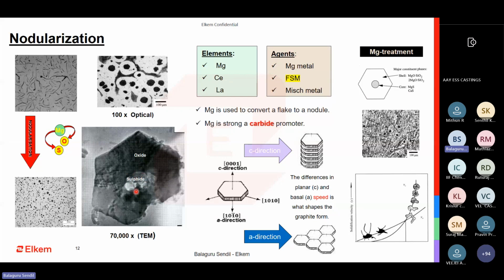To make this nucleus, magnesium sulfide or magnesium oxide, and with recent developments in nucleation theory, we see magnesium nitride is also very important. All these are the nuclei, non-metallic, but all magnesium, cerium or lanthanum based. The process of introducing magnesium to a metal to convert a flake to a nodule is called nodularization. The magnesium you add combines with the sulfur, oxygen, and nitrogen available in the metal, and forms magnesium oxide, magnesium sulfide, magnesium nitride, multiple non-metallic components, and becomes a nucleus, a point where the carbon can deposit, grow, and form a nice nodule. So this is the process of nodularization.